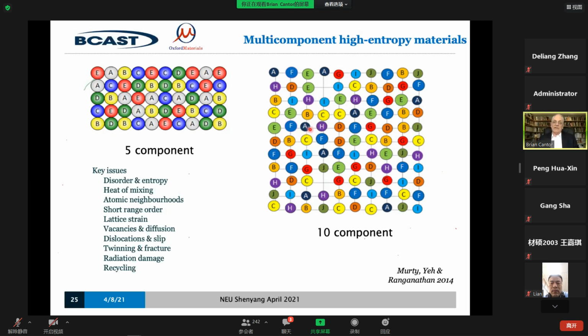How many different local environments are there? Well, if we take the Cantor alloy with 5 components on FCC, where there are 12 near neighbors, so a local cluster is 13 atoms. How many different 13 atom clusters are there if you have 5 components? I tell you the answer, it's 20 trillion. It's a very big number, 20 trillion. It's so big that if you want to have an average material, you need to extend the material enough to encompass all different local structures. And to do that, you need to have a piece of material which is several microns in dimension. So if the grain size is smaller than about 20 microns, each grain of the material will be different. That's for the Cantor alloy.